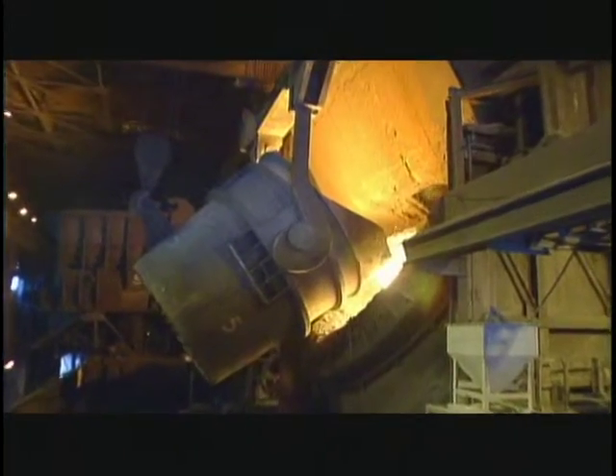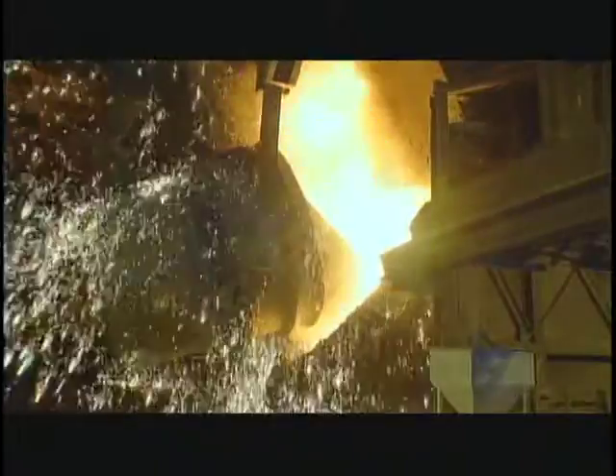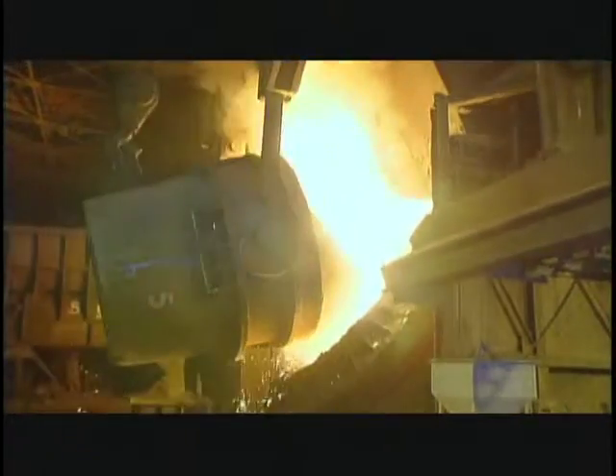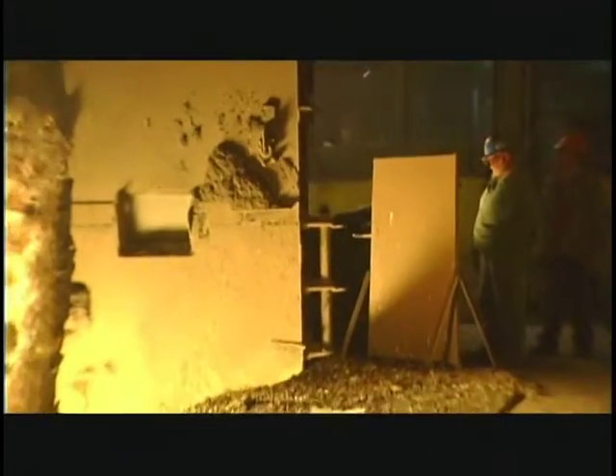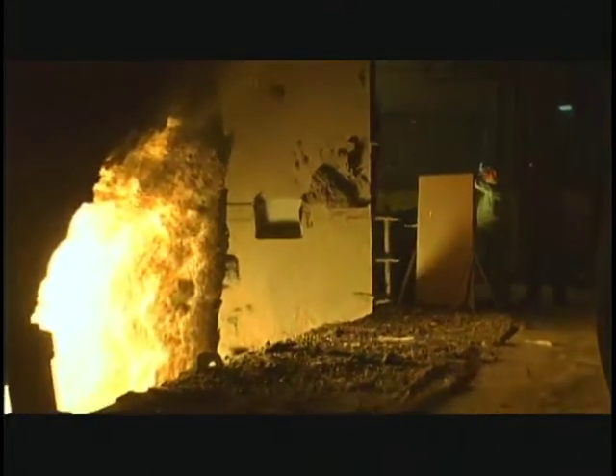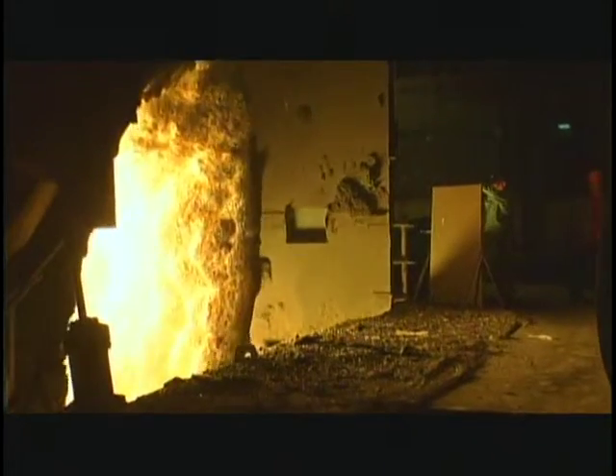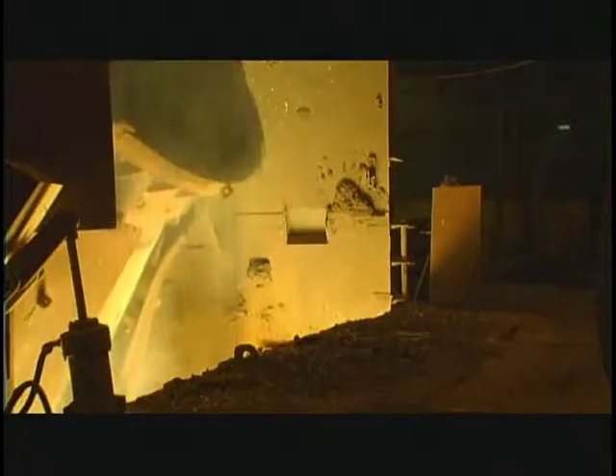To get the heat, we top blow with an oxygen lance, oxygen at 3,000 cubic feet per minute. We inject it at about Mach 2.2. And at the end of the blow, in about 18 minutes, we analyze it. If the analysis is good, then we'll tap the heat, and we've made 305 good tons of steel.